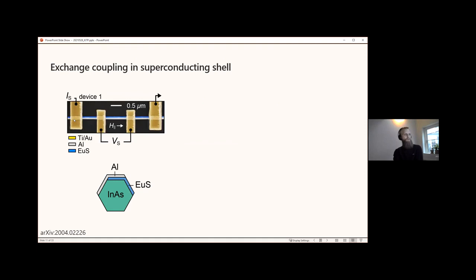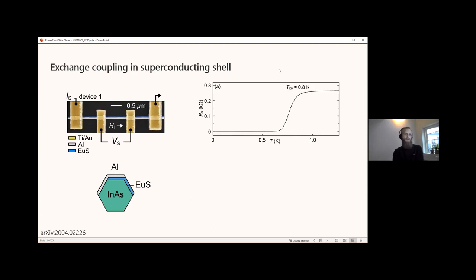So we took a single nanowire and contacted it with four normal leads, allowing us to measure the voltage drop along the superconducting shell as a function of current bias and parallel magnetic field. Notice that there are no weak links or anything, so it's really just the properties of the superconducting shell, where the semiconductor acts as a substrate, if you will. Cooling this wire down and measuring the differential resistance, dV/dI, we found that the critical temperature at zero applied magnetic field is around 0.8 Kelvin, which compared to the bulk of the aluminum, where the critical temperature is 1.2 Kelvin, is already decreased, indicating that europium sulfide is probably doing something to the aluminum.